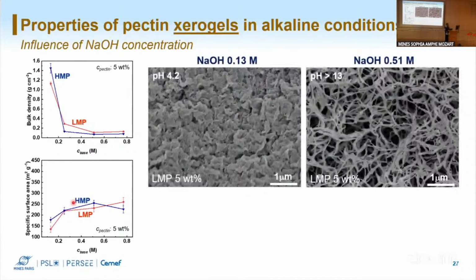We can see the structure again. So in this case, when we have very, very high bulk density, we can see the structure of our material that is very dense. We cannot really see the porosity. And when we go to high base concentration, we get a very nice structure. Not as nice as acidic pH maybe, but we have very open pores and well-defined fibrils.